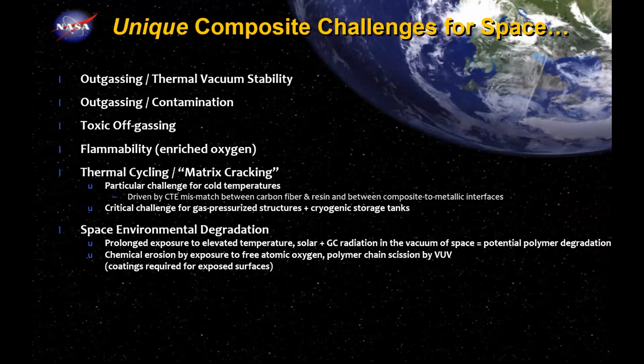Thermal cycling is a big one. Matrix cracking: when you get really cold, especially in those cryogenic applications, they tend to micro crack. That's a problem not only for cryogenic storage, it's a problem for habitats. Because if you get matrix cracking, gas leaks, and you keep sending tanks to the moon trying to replenish the gas. We don't have enough tanks coming.